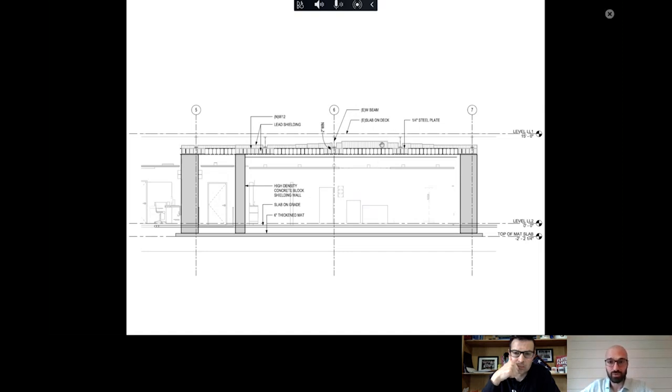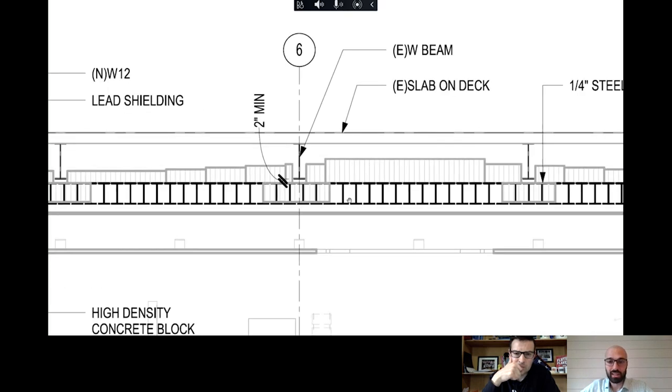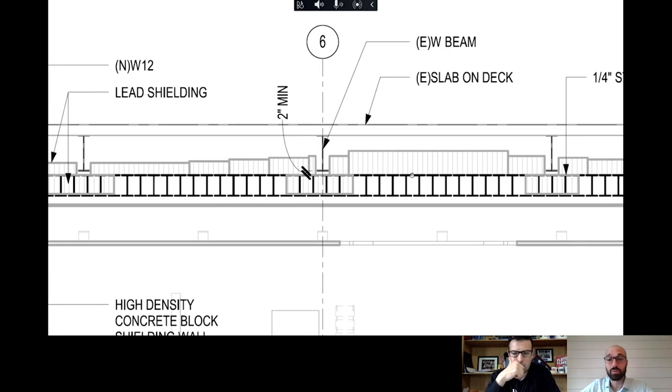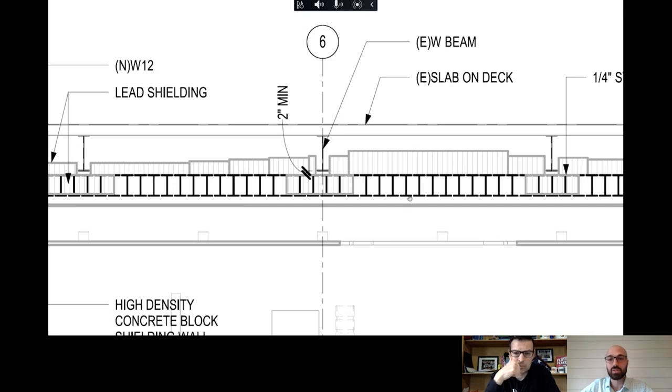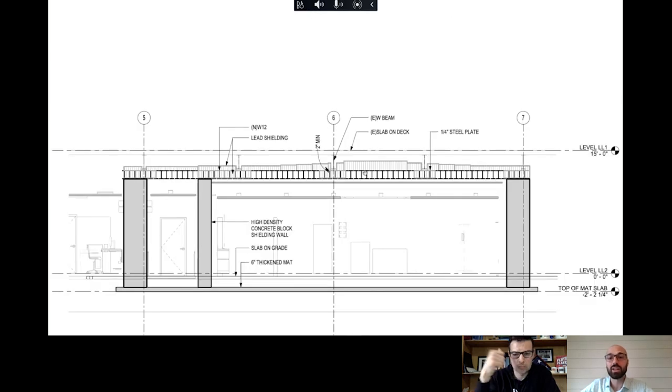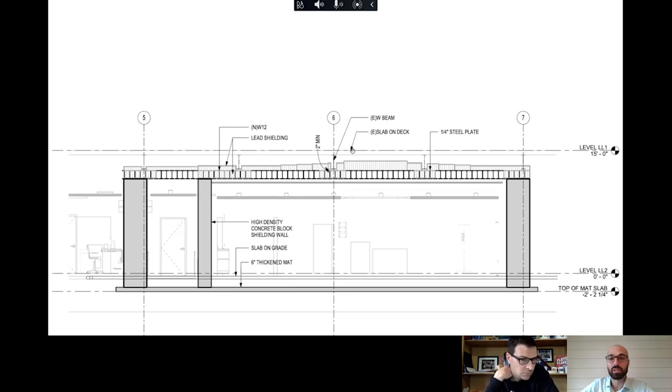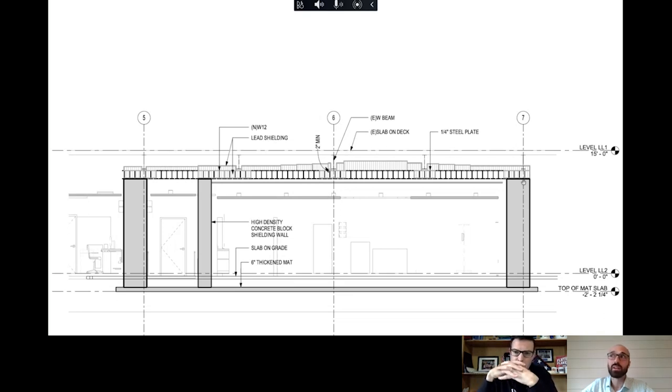And I sort of lamented the fact that we couldn't do this out of cast-in-place. The ratio of lead to this high-density block in terms of its shielding properties is about three inches to one. So for every inch of lead they had on the ceiling, we needed three inches of concrete block. And it just so happens that that dimension is exactly 28 inches, which is the bottom of this I-beam to the top of the slab on deck above. So the initial idea was, let's remove the building structure, place a cast-in-place vault with the top of the vault replacing the existing interior slab. You could put carpet down on it. Nobody would be the wiser.